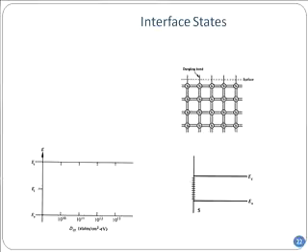So if you just make an estimate, the number per centimeter squared on a 100 surface would be on the order of 10 to the power 14 per centimeter squared, and if you didn't do anything, that is the number of defects you would have had. That's the blue line. Number of defects you would have had: 10 to the power 14 per centimeter squared. That's a huge number of defects.